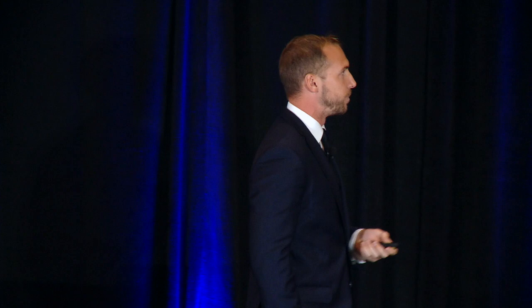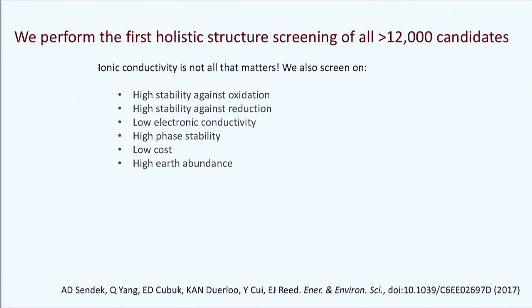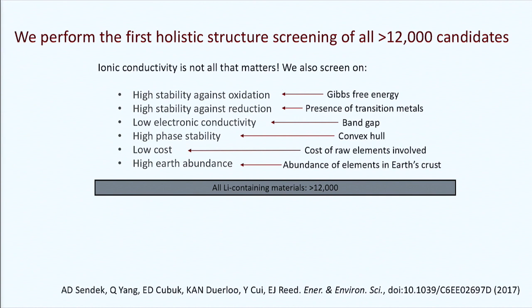This equation is so fast that we can turn it loose on every known lithium-containing compound. We also put together an additional six screening criteria capturing things like stability. We turned these seven screening metrics loose on more than 12,000 lithium-containing compounds. Screening on the six non-conductivity criteria gets us down to 300 — still too many for physics-based methods. Using the ionic conductivity predictor, we get this down to 21 candidates, tackling several parts of the performance diagram we couldn't address before.